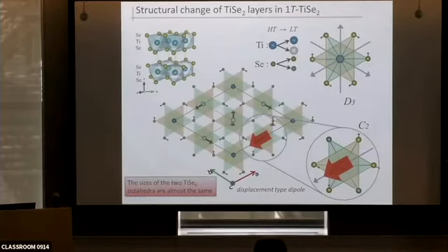On the other hand, one TiSe6 octahedron has an electric dipole type displacement, by moving titanium and selenium in antiphase in the AB plane. Please note that this displacement dipole is different from the electron dipole corresponding to excitons.